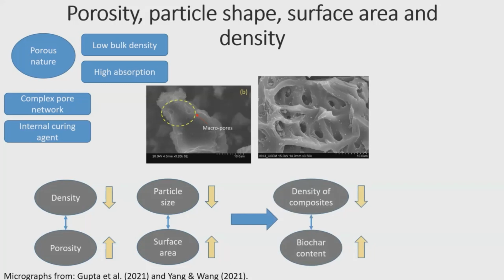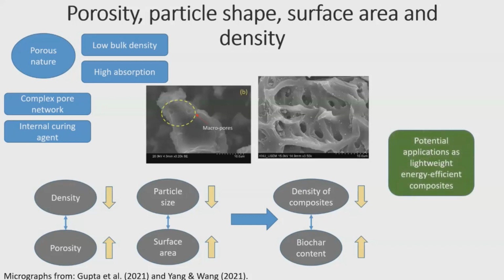In the context of biochar, which is a porous material and tends to have lower densities, depending on the calcination temperature, tends to have lower particle sizes on the lower end, which develops composites of a lower density. And this is heavily affected by the ratio of biochar replacement. However, this is not all bad news, because biochar cementitious composites might pose potential applications as lightweight composites, which are energy efficient.